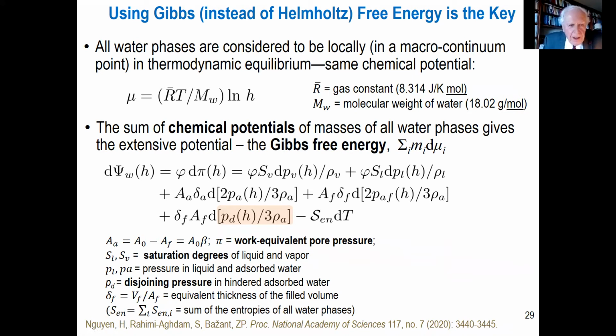So we recognize the fact that the Gibbs free energy of water in a unit volume of concrete is a sum of the Gibbs free energies of all the phases. In thermodynamic equilibrium, Gibbs free energy, or chemical potential per unit mass, must be equal in all the phases. So you sum the masses times increments of chemical potential to get the total increment of chemical potential, which is the free energy psi of water in concrete. Now, there are different phases. First of all, we have porosity, which you must know. And then, by definition, what multiplies it is the equivalent pore pressure, equivalent thermodynamically, although partial pressures are, of course, very different.